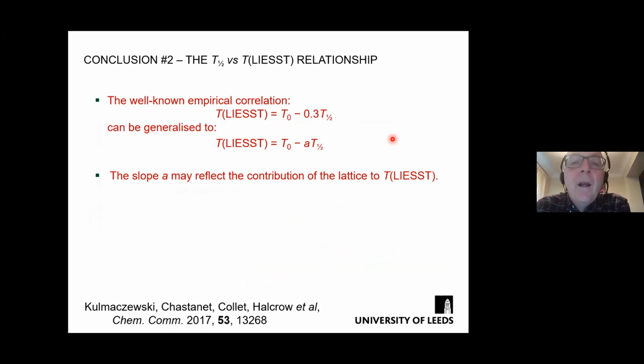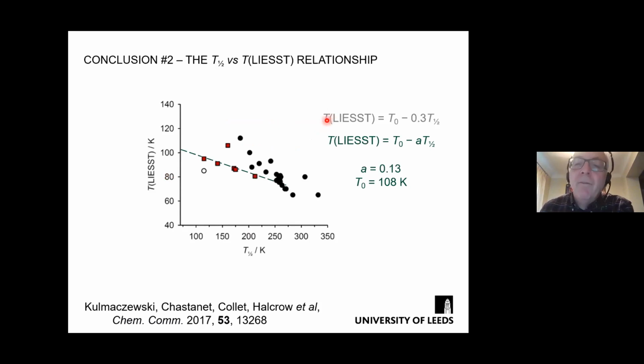So to finish, we have a few conclusions from this study. First is that the well-known linear relationship between the thermodynamic and the kinetic spin crossover exists, but it's a little more general. It's not this simple equation. In fact, different materials will give you different relationships, and the slope of the line here, I think, tells you something about the crystal lattice of your material and how it contributes to the activation energy of the LIESST relaxation process.